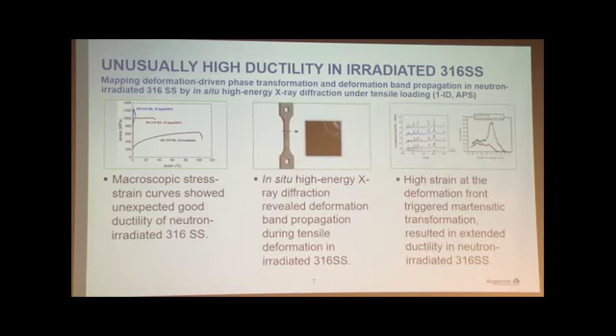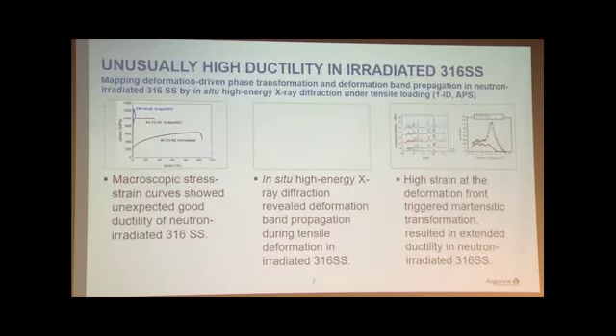During the tensile test, we used an X-ray to scan the specimen gauge. We found the diffraction pattern along the specimen gauge. I don't know if the movie shows. Okay, so it's actually the diffraction data along the specimen gauge is very different.